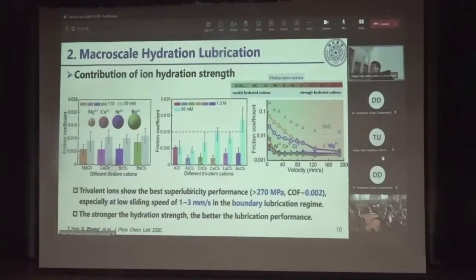Then, according to the Hofmeister series, we know that the divalent and the trivalent compounds have stronger hydration effect than the monovalent compounds. So we do the test using divalent and trivalent compounds, and we found that all these divalent and trivalent compounds can obtain a very low friction coefficient, and the contact pressure is also very high, about 270 megapascal.